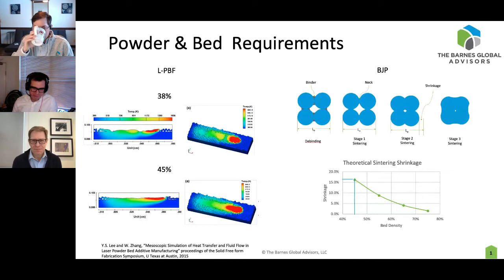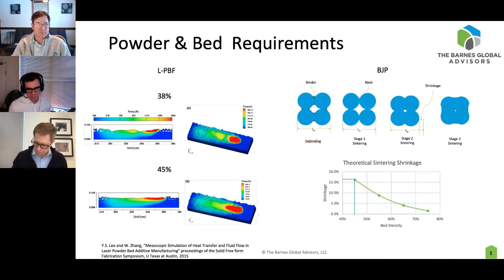So what I'm taking away from this slide is that the types of requirements we put on the powder going into a laser powder bed fusion space are very different than what we would typically care about for binder jetting. Understanding particle-to-particle interaction on an individual particle level is going to result in very different structures. In powder bed fusion we undergo an entire phase change from solid to liquid in our melt pool track, but in binder jetting we never achieve that. So a very different set of steps has to occur to arrive at both a functional and as fully dense as possible part.